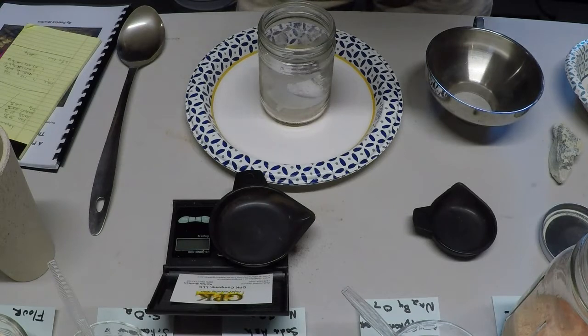Arsenopyrite, let's see if I can find it here, also reduces lead at a lesser rate. Yeah, arsenopyrite will reduce approximately 4 grams of lead oxide to metallic lead per gram of arsenopyrite. Now what we did when we roasted our ore was we added a little bit of charcoal to it while we were roasting it, to reduce any excess arsenic that wasn't driven off in the initial roasting process to another arsenic compound, and then we vaporize it off. Arsenic really causes a lot of trouble in your fire assays. So we got rid of that.